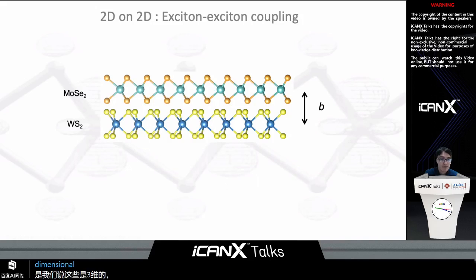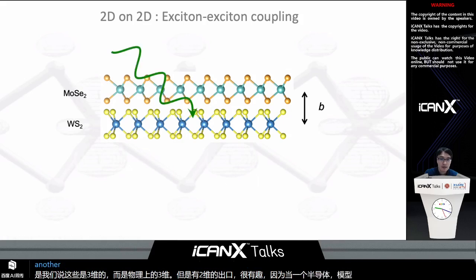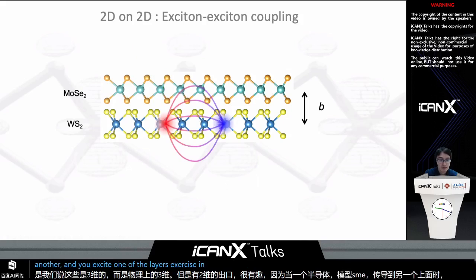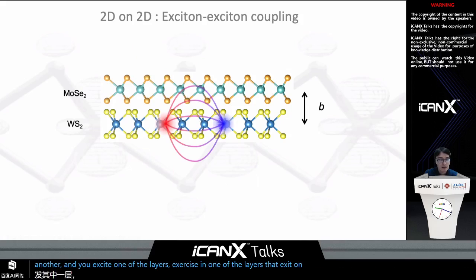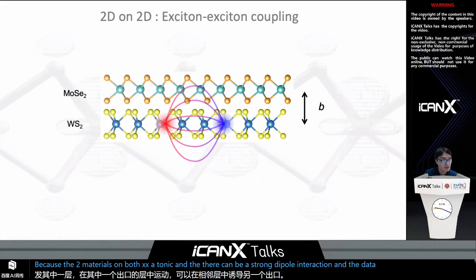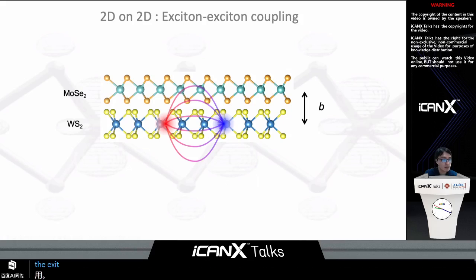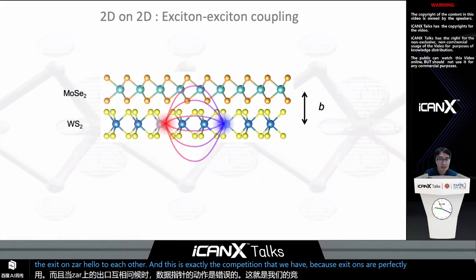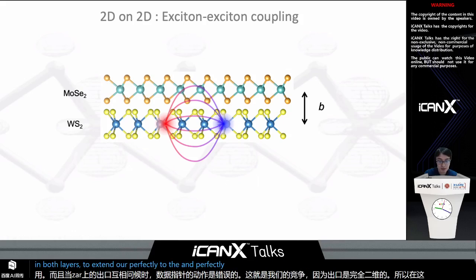Now, having two-dimensional excitons is interesting because when you put one monolayer semiconductor on top of another, and you excite excitons in one of the layers, that exciton can induce another exciton in the neighboring layer, because the two materials are both excitonic, and there can be a strong dipole-dipole interaction. And the dipole interaction is strong when the excitons are parallel to each other. This is exactly the condition that we have, because excitons are perfectly two-dimensional. So in both layers, the excitons are perfectly 2D and perfectly parallel to each other.